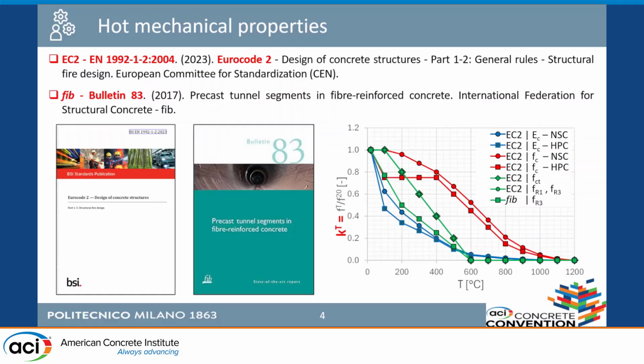An important aspect is the Young modulus, or the elastic modulus. Eurocode 2 does not give the decay of the Young modulus, but it gives us the constitutive law for any temperature. So by just calculating the slope at the beginning, we can work out the elastic modulus. Pay attention that it's not correct to use the term elastic modulus, because during heating, we don't see just instantaneous deformation, but we also see creep. And the problem of high temperature is that creep is very fast. So in the few hours in which we have heating, we see the creep effect that can double or even more the deformation within concrete.